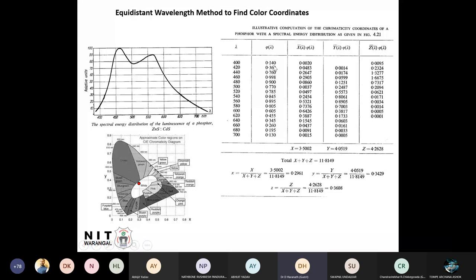Because you see around 450 or so, you have the peak. Here at 460, it is 0.998. Maybe at 461 or 462, it is 1. So this peak is normalized to 1, and all others will be lesser than that. Everything, the intensity values, is put here.